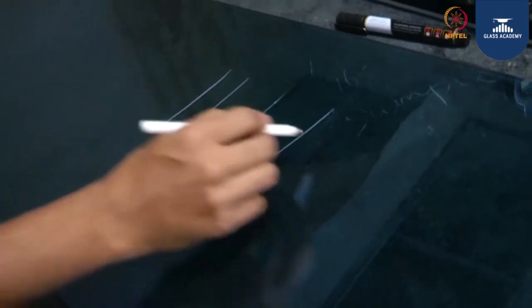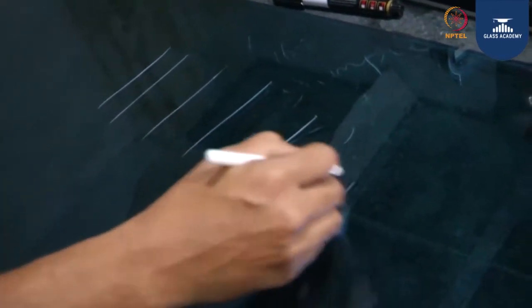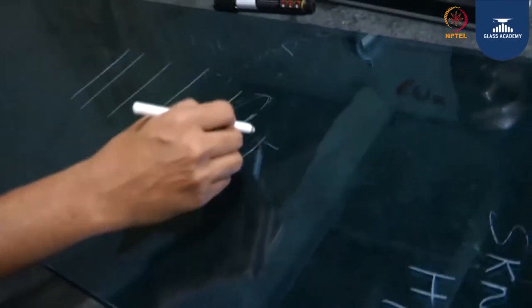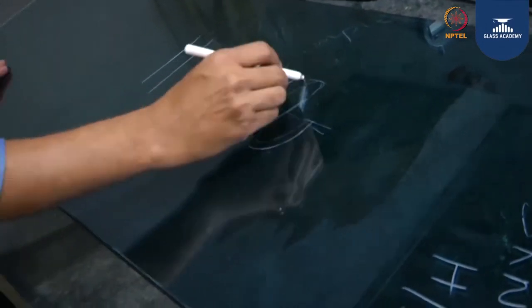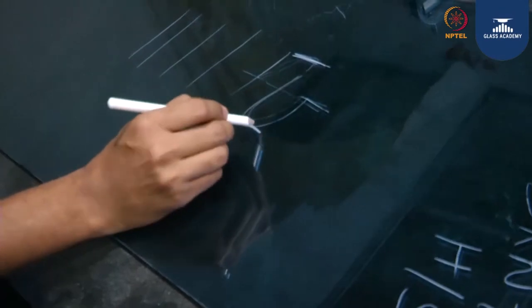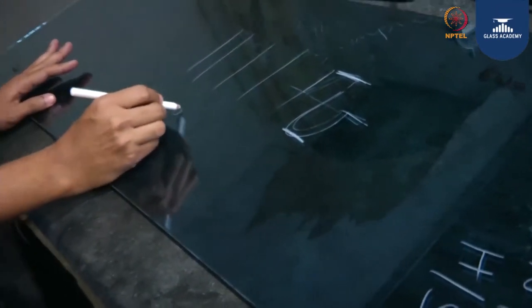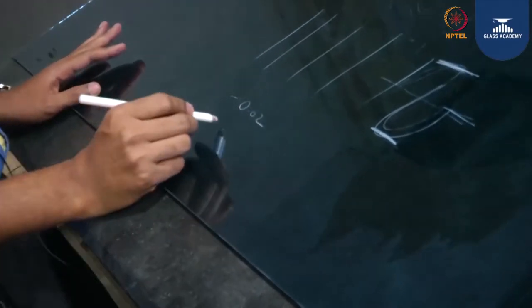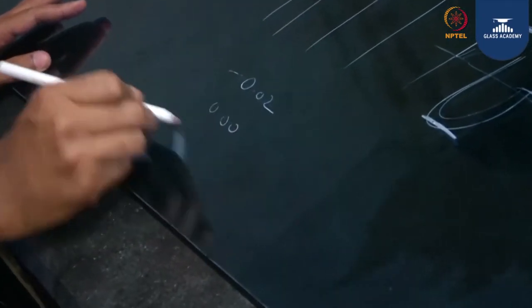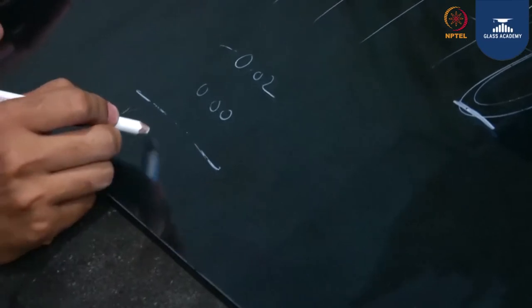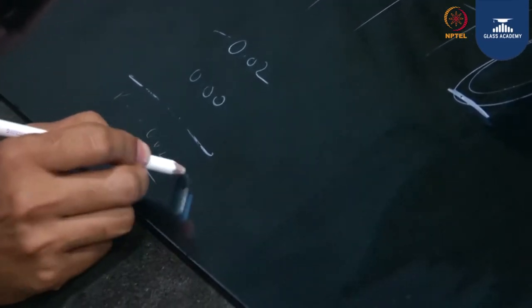As the glass is moving through rollers, it will be acquiring a sinusoidal wave, and one complete cycle will give me the roller wave. It is a summation of peak and the valley. The minimum value we get is minus 0.02, and the maximum value we got is 0.00. So the overall roller wave is equal to 0.02